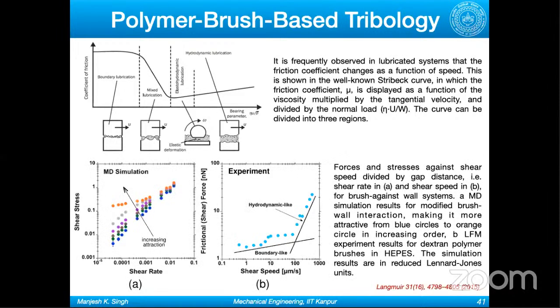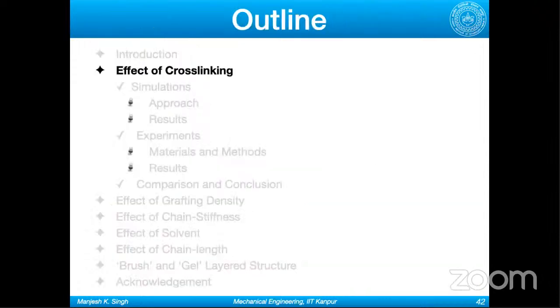But if you look at this polymer brush-based lubrication, these are my simulation results, and these are experimental results from one of my colleagues. What you see is that you have a hydrodynamic lubrication regime, you have a boundary lubrication or boundary-like regime, but you don't have any mixed lubrication. So you just go from boundary to hydrodynamic. You don't have any mixed lubrication regime in between, which makes it very interesting as well. This is just to give you information. If you are interested, you can read more about it.